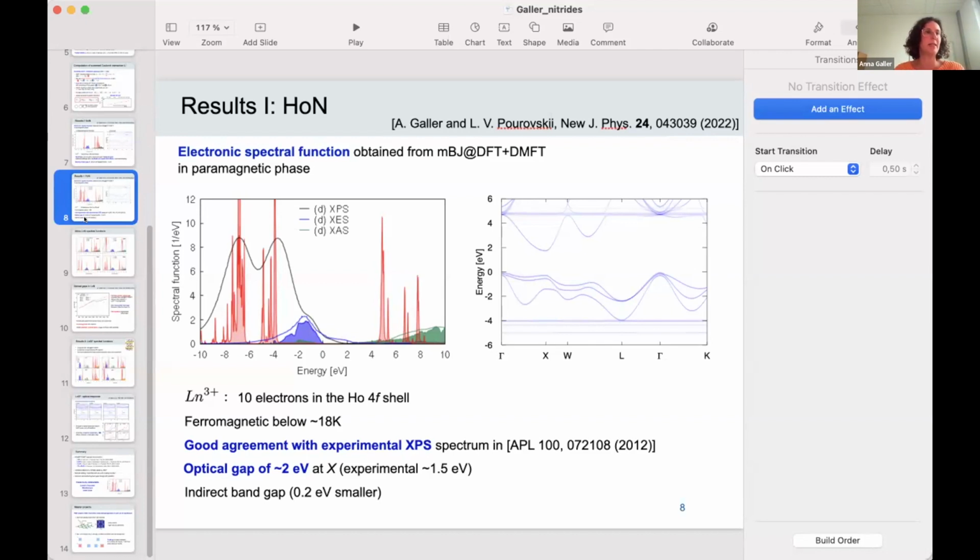You can do pure DFT or DFT with MBJ in order to get the electronic structure. Okay, great. Because I know at the PBE level you can still get a metal, but the special sauce there, you just need the MBJ, it sounds like. Yeah, in order to open the band gap, you need a semi-local, or such a hybrid functional. Right. Thank you so much. Or GW to open the gap there. Yep.